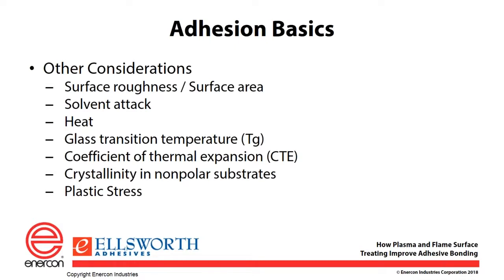If you're dealing with a high service temperature and you have an adhesive where you move through the glass transition temperature in your application, it's important to evaluate the adhesive at that elevated temperature to make sure that you still retain your bond, because a lot of materials will start to have lower bonds as the temperature is increased.